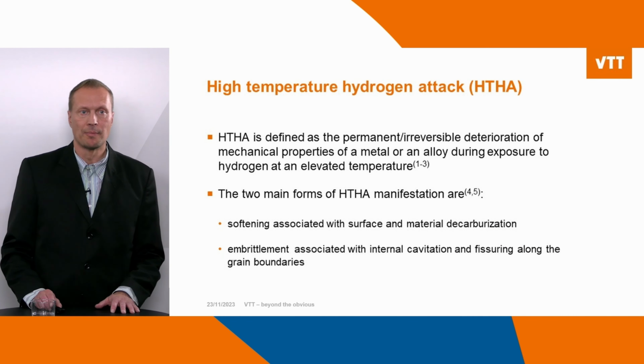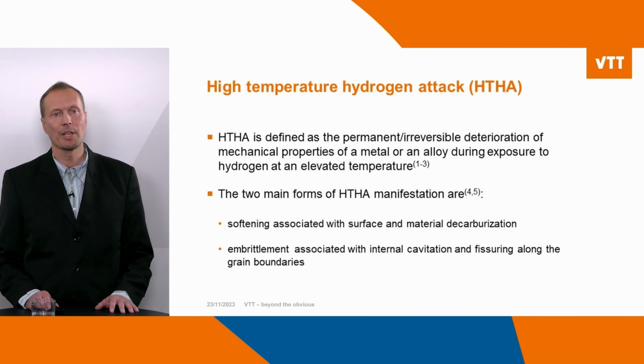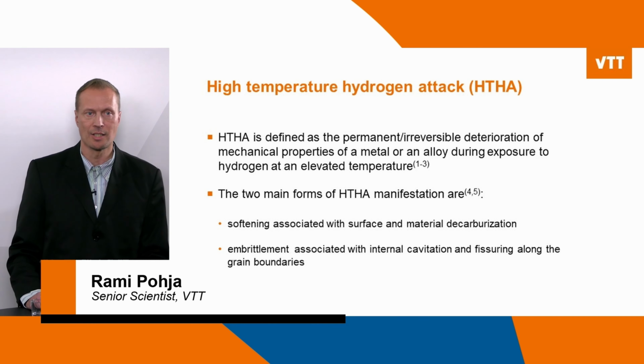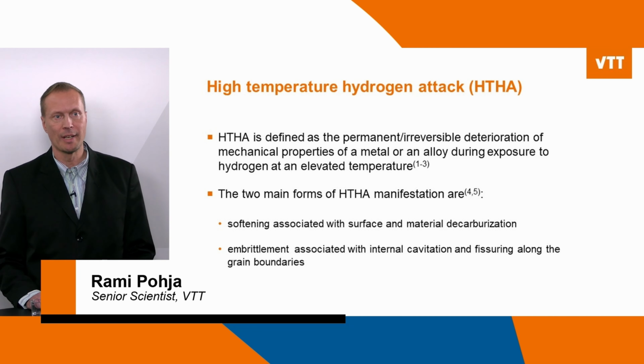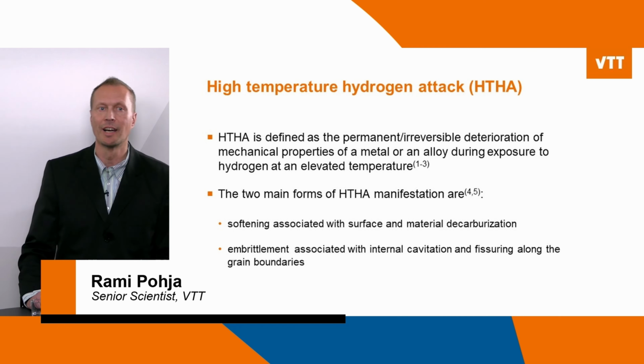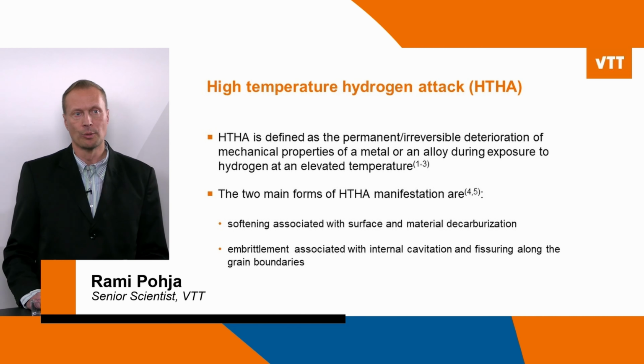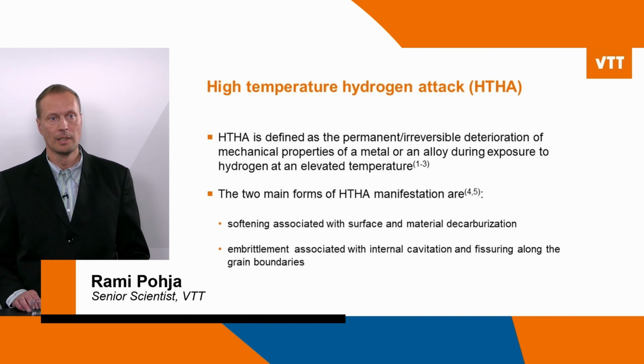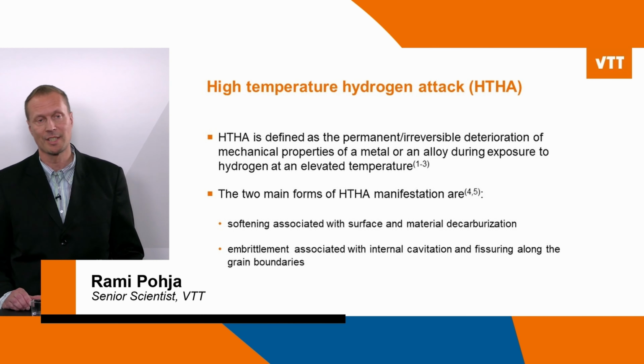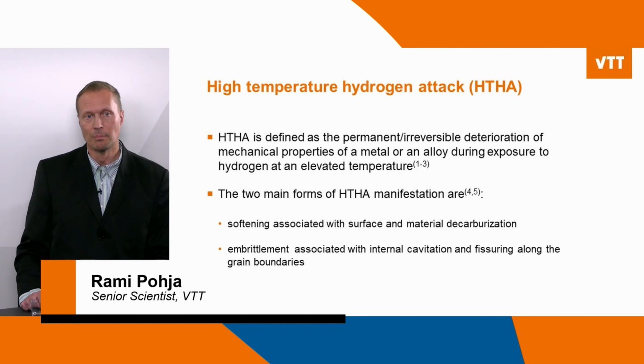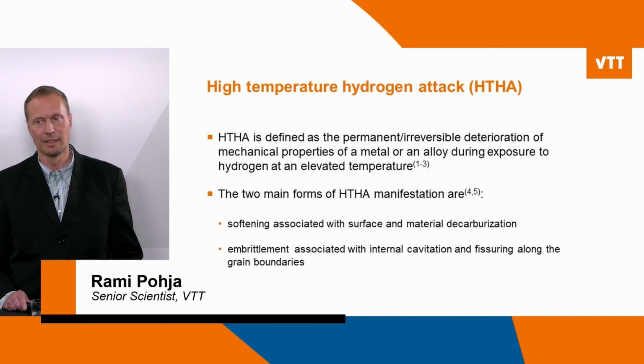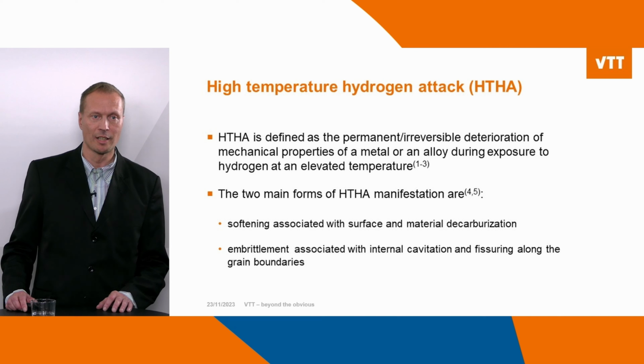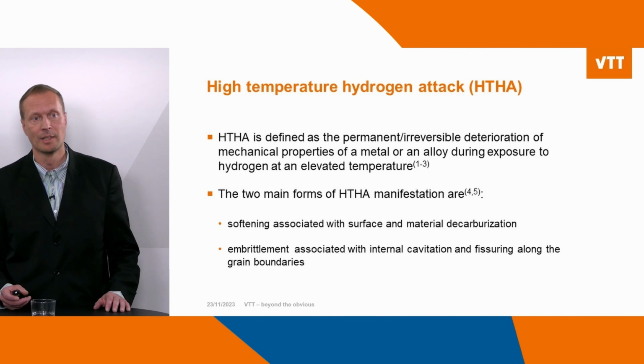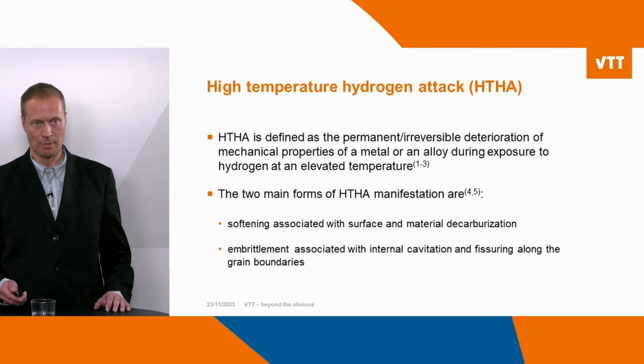Then some words about the high-temperature hydrogen attack. High-temperature hydrogen attack is defined as a permanent and irreversible decrease of mechanical properties of a metal or an alloy during exposure to hydrogen at high temperatures. These two main forms of high-temperature hydrogen attack manifestations are firstly softening, which is associated with surface and material decarburization, and secondly embrittlement, which is associated with internal cavitation and fissuring along the grain boundaries due to these methane bubbles.